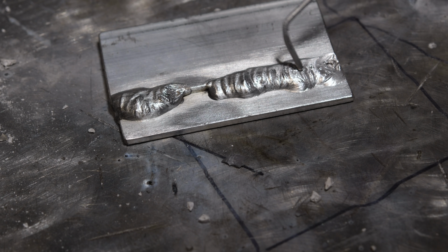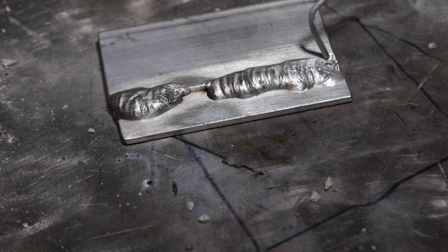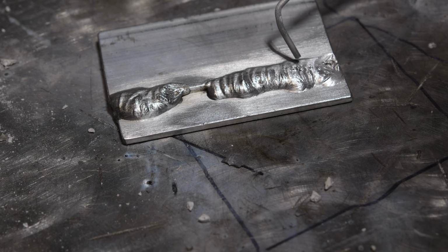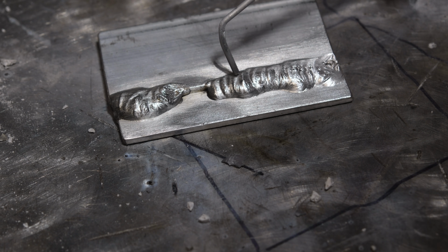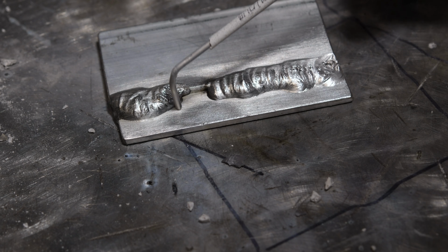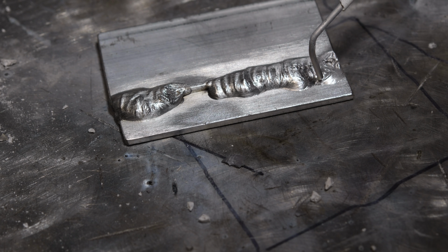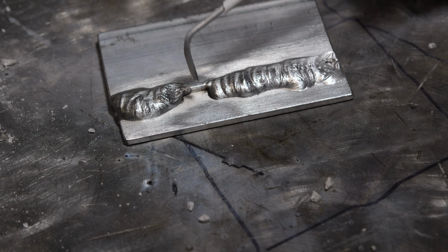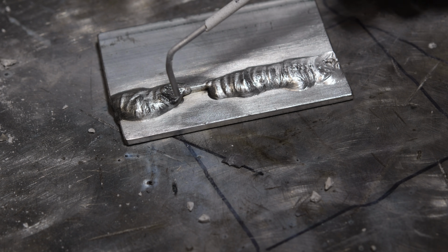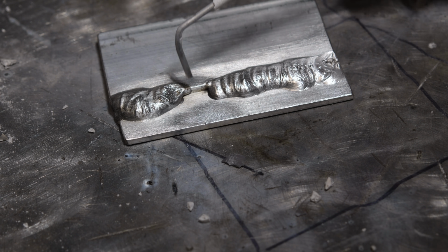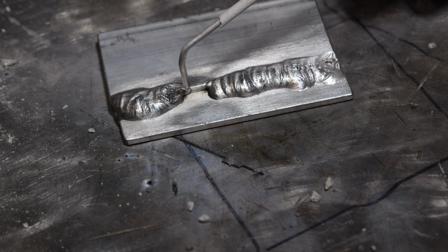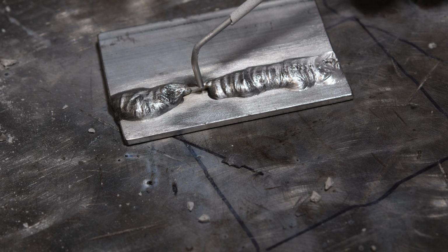Well, there's porosity in here as well as on the end. I tapered out slowly, but it's so difficult to see what's going on, and honestly, I don't even know that it really matters because you're just going to get defects doing this. Now, is this a weak weld? Realistically, due to the already visible defects, yes. The cold lap, even this bottom looks a little bit cold, that it didn't fuse, which has more to do with the surface oxide not allowing the metal to fuse. Because remember, that oxide layer melts at a higher temp than the actual aluminum under it.